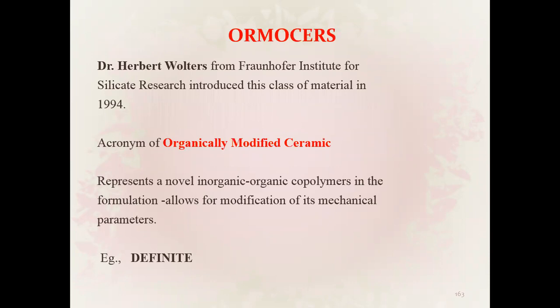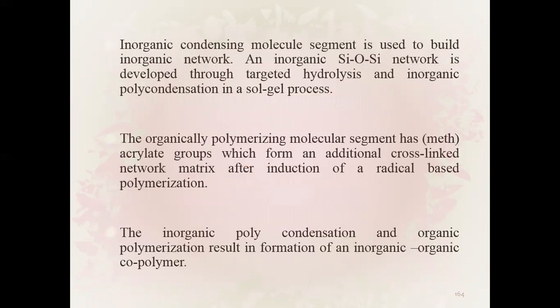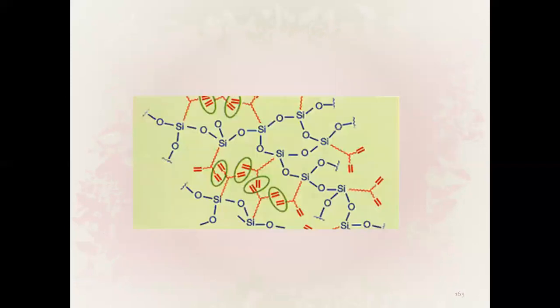Ormocers: Dr. Herbert Wolters from the Fraunhofer Institute for Silicate Research introduced this class of material in 1994. Ormocer represents organically modified ceramic — a novel inorganic-organic co-polymer. An inorganic silicate network is developed through targeted hydrolysis and inorganic polycondensation in the sol-gel process. The organically polymerizing molecule segment has methacrylate groups which form an additional cross-linked network matrix after induction of radical-based polymerization. The inorganic polycondensation and organic polymerization result in an inorganic-organic co-polymer.